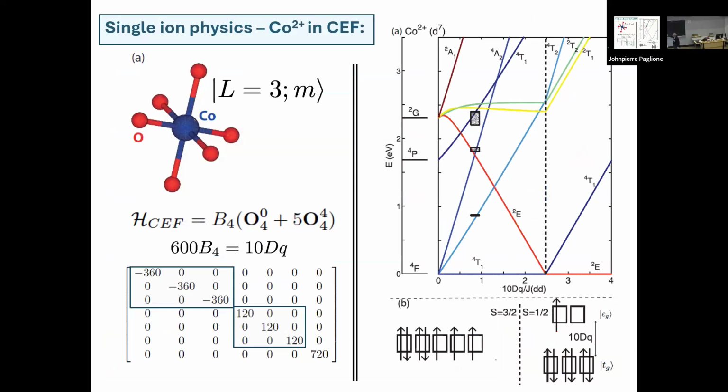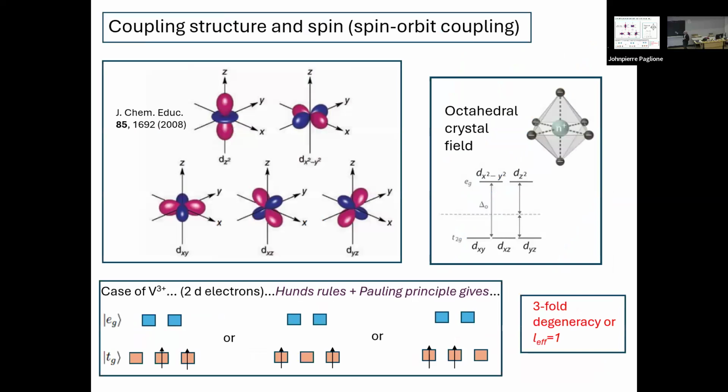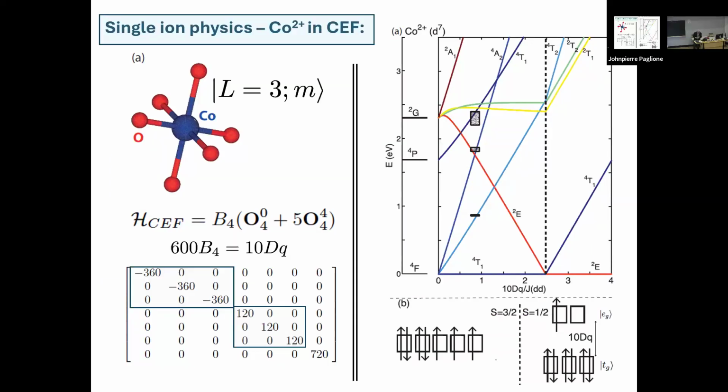That turns out, in the case of an octahedral field, to work out exactly. I'll say a few words about that in a few minutes. But if you do the crystalline electric field and work out what the orbital levels are, you end up with this ground state triplet there. Now, going back to these 2 effects I was talking about on the previous slide, we had the splitting between the d orbitals, which is set by this energy scale delta, which is set by the oxygen atoms, for example, that are sitting around there.